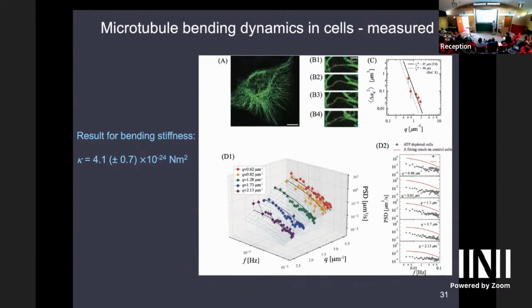So if you isolate microtubules from brain, for example, and reconstitute them, you probably get defects. And you also get, and that's something I'm going to come back to, many post-translational modifications in microtubules in cells. And if you isolate them from some tissue, you get an unknown mix of all these things. And so it's probably a bit of a mess, and they're kind of sensitive structures. And so the in vitro data have to be taken with a grain of salt. But that makes it even more important to measure these properties in cells. And so that's the main reason why we did that.